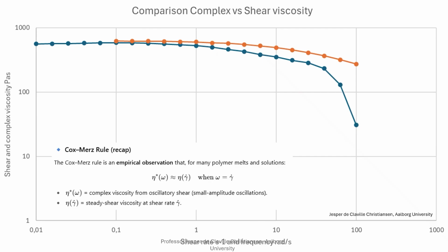Many times the so-called Cox-Merz rule is used, where you measure viscosity in oscillation and assume that the complex viscosity is similar to the shear viscosity, and that instead of the shear rate, you can plot the frequency in radian per second. It's a very, very common assumption, but I've done it here for these measurements on the polypropylene, and you can see that the curves do not coincide. So the conclusion is that the Cox-Merz rule is not valid, but it gives the same Newtonian viscosity, the viscosity at very low shear rates. You can also see that the shear thinning effect is much stronger in the real shear data than in the oscillatory data, which can be expected from the orientation of the chains at higher deformation rates.